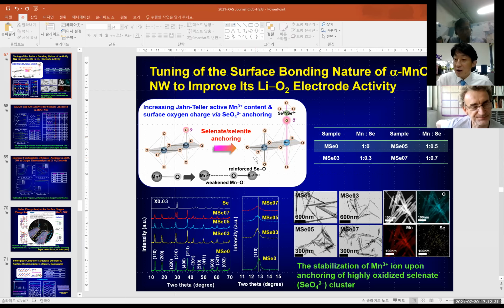The crystal growth of the alpha MnO2 lattice and the attachment of the selenate nanocluster occur at the same time. So there are actually two effects. The incorporation of such a high oxidation state leads to the lowering of the average manganese oxidation state. Also, in terms of chemical bonding, the selenium-oxygen bond is much more covalent and stronger than manganese-oxygen. So in terms of bond competition, it leads to weakening of the neighboring manganese-oxygen bond and elongation of the axial bond distance. It is one of the contributing factors that stabilize the tetragonally distorted manganese oxide. So the objective is to produce more Mn3+. Yeah, right.